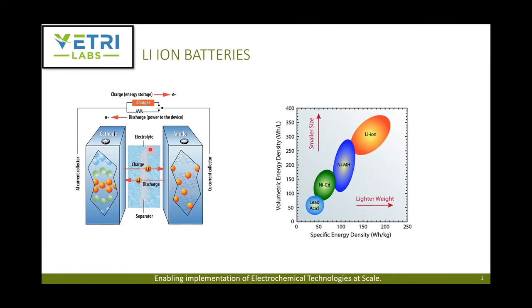And for the electrolyte, there's a separator that's typically polymeric with some ceramic material added to it for structural stability. And typically a non-aqueous electrolyte is used because lithium is water sensitive, so the electrolyte is an organic electrolyte. The reason lithium-ion batteries have become very popular is the energy density. Both volumetric energy density, given in watt-hour per liter, as well as gravimetric energy density, which is watt-hour per kilogram, are much higher for lithium-ion when compared with nickel metal hydride, nickel cadmium, or lead acid batteries.